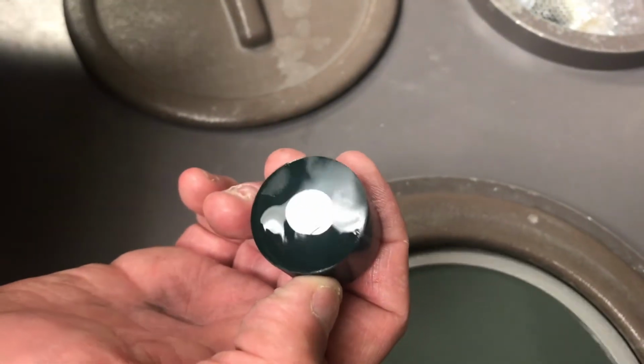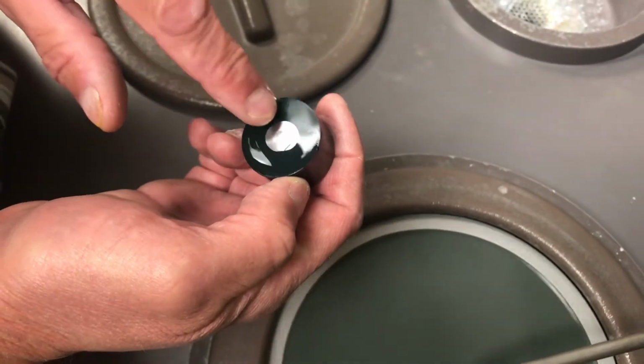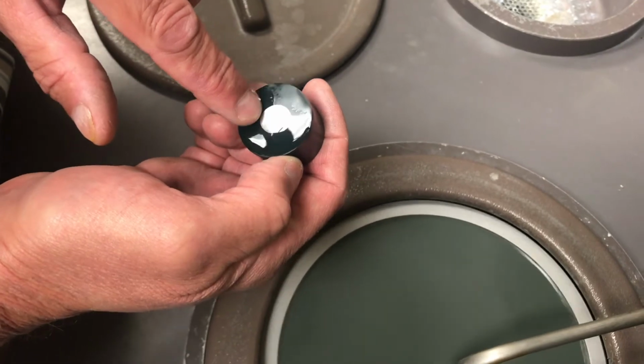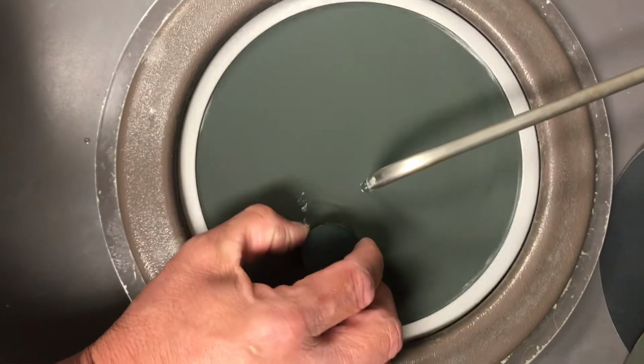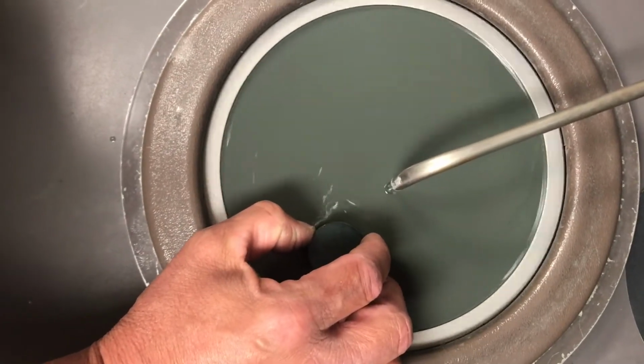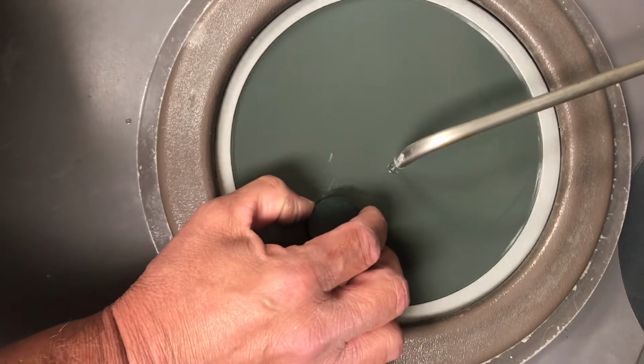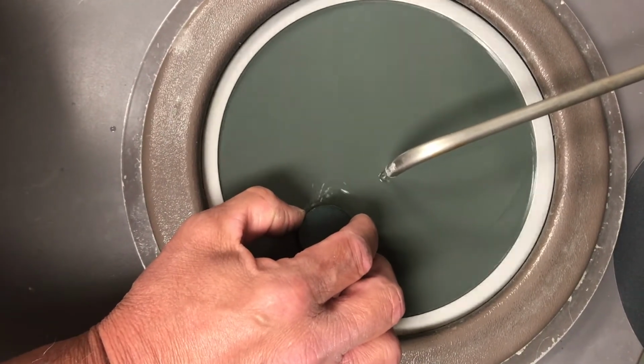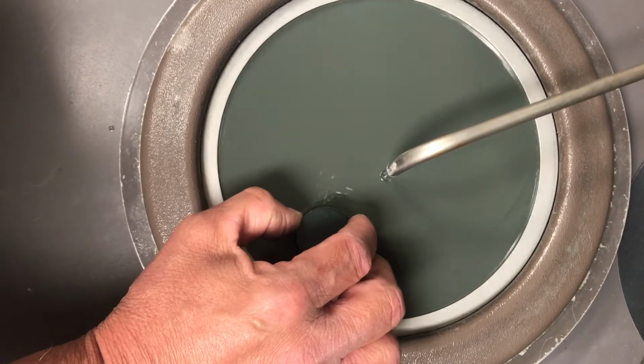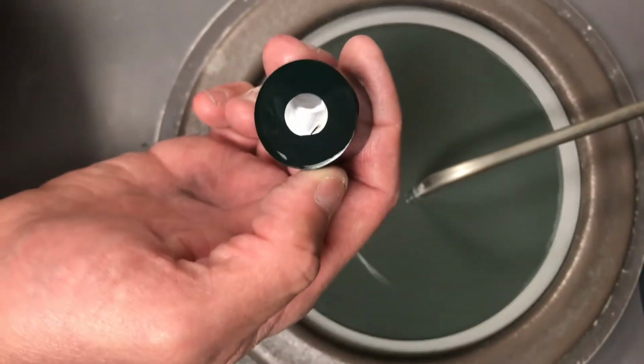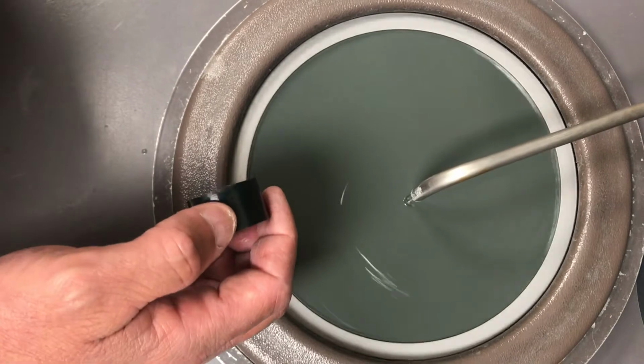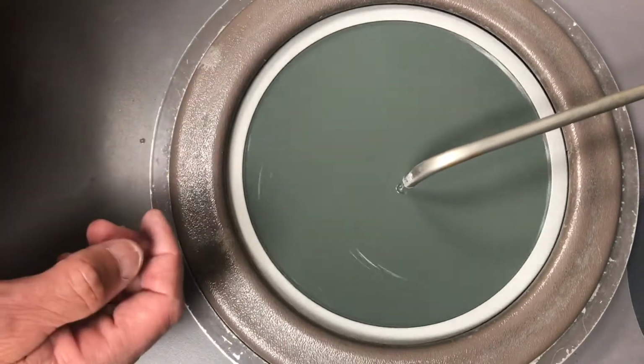Now, we're not there yet. The sample is clearly not there. You can see that it's slightly polished here, but not here. So we're going to need a significant amount of time, maybe 5 or 6 minutes anyway, to achieve a uniform surface. But we'll get there. Just keep going until you see a uniform surface.